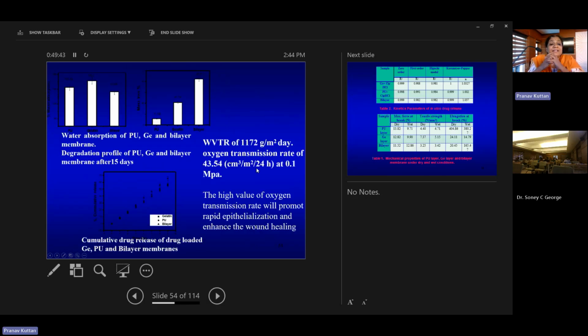Then it is important that we study the water absorption of these different layers independently and also as the bilayer. The left side is the water absorption of polyurethane, gelatin, and the bilayer membrane. All the membranes show a considerable amount of water absorption, which is again a good property for wound healing. And the right side is the degradation profile. The mass loss is very low for polyurethane as expected, since it's a synthetic polymer. For gelatin, it is even higher. But when it is in combined form, it degrades faster. So that is also one important parameter which is required.